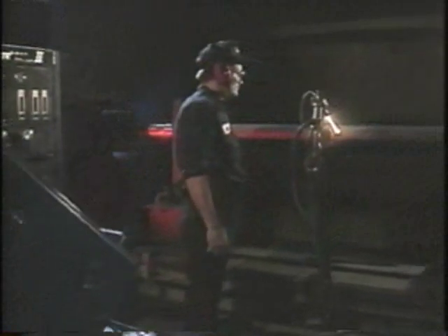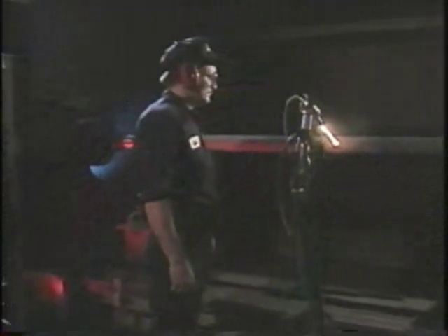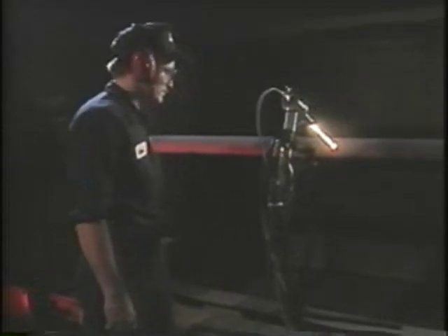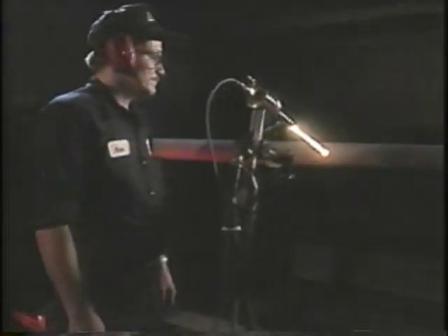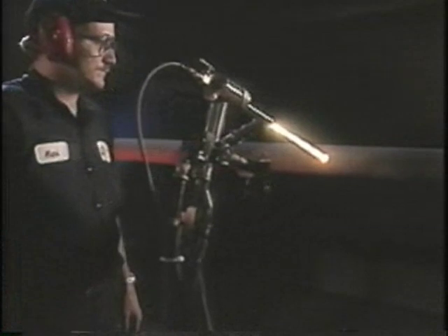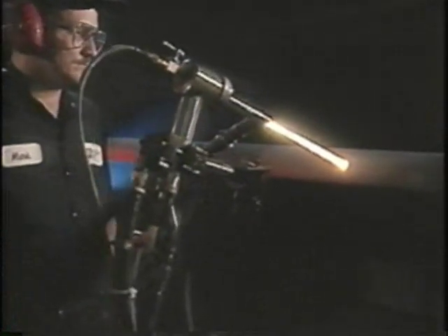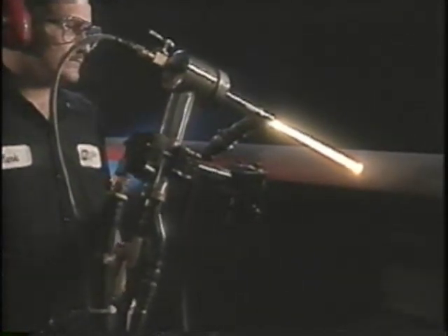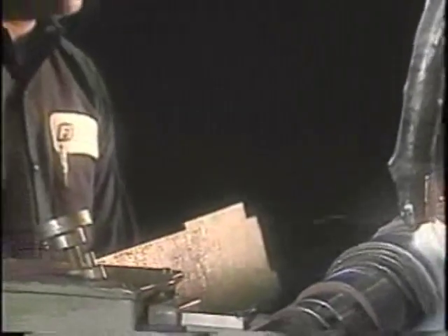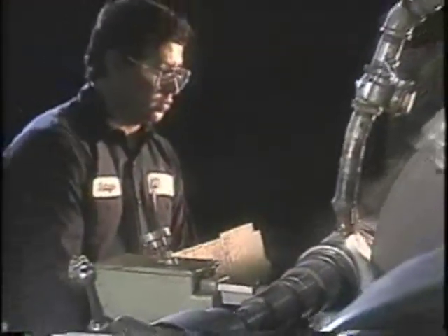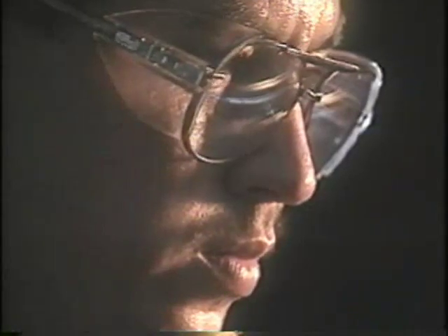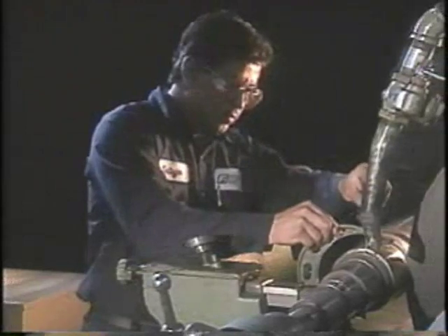This high-velocity oxy-fuel method lays down a coating with terrific bond strength and low porosity. That means it works well on high-speed rotating equipment as well as in high-pressure service. To allow for finish grinding, the coating is built up 10/1000ths over the finish dimension. Diamond wheels are used to grind the carbide coating back down to spec, guided by extremely precise equipment. During the process, the operator with many years of experience will closely monitor size, concentricity, and taper.